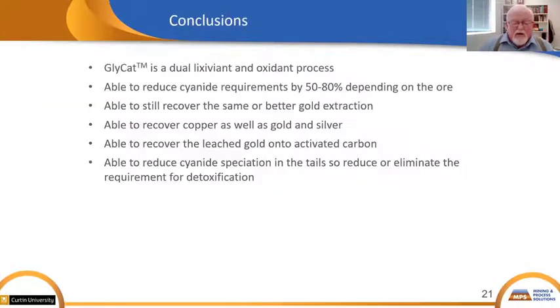Well, summing up, Glycat is a dual lixiviant and oxidant process. It's able to reduce cyanide requirements by 50 to 80% depending on the ore. It's also able to recover the same or better gold extraction. It's able to recover copper as well as gold and silver. It's able to recover the leached gold onto activated carbon. And it's able to reduce cyanide speciation in the tails, so as to reduce or eliminate the requirements for detoxification.